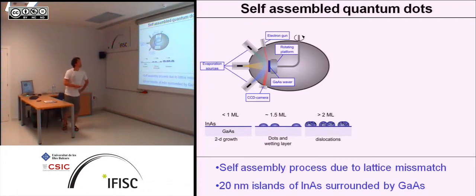So the quantum dots I studied were self-assembled quantum dots, made of semiconductor material. For that, you have a gallium arsenide substrate, and you use molecular beam epitaxy to basically put a vapor of source materials on top of that. The evaporation source in our experiments was indium arsenide. If you now grow a layer of indium arsenide on top of gallium arsenide, the lattice mismatch between the atoms of the two different materials leads to strain.